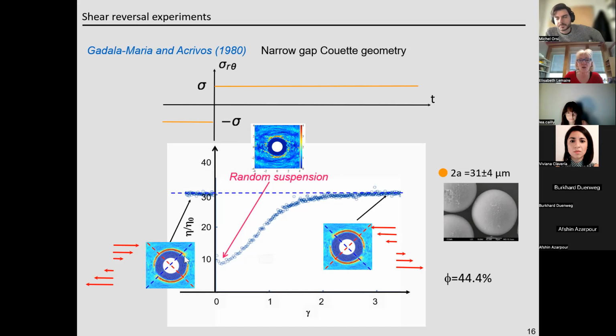But of course, it's linked, because if your microstructure is orientated along the dilatation axis direction, then when the flow goes on, the contacts are broken. So of course it's important, but when you make the calculations, what matters is really the number of contacts between particles. Correct me if I'm wrong, Elisabeth, but the PDFs in this case are a signature of the contact. So you can use the PDF to show that the particles are in contact with each other, and that's what has an impact on the macroscopic scale, the presence of contacts.